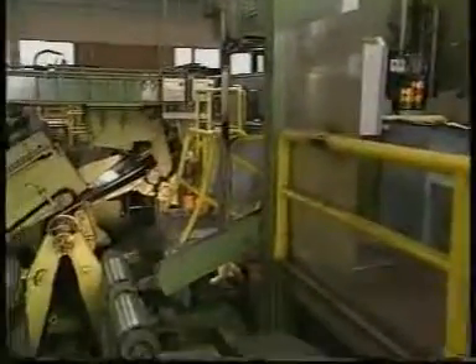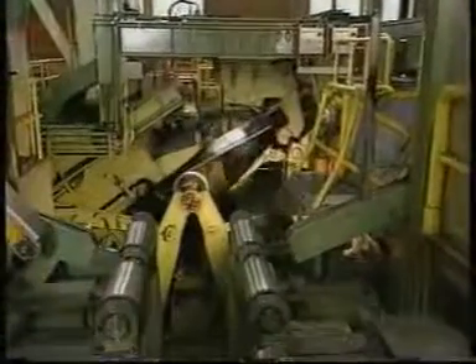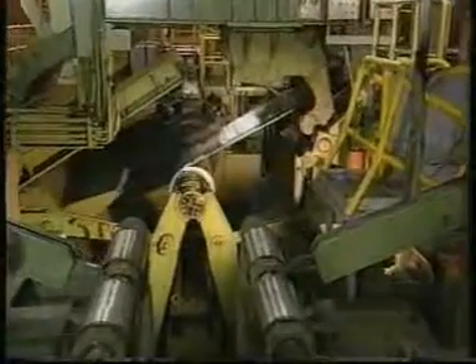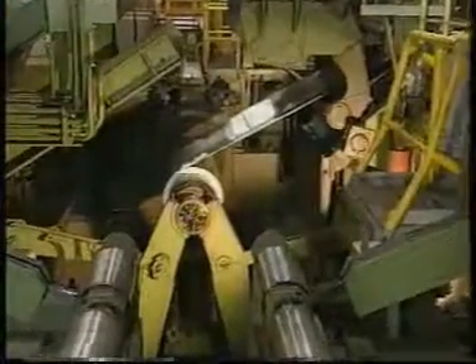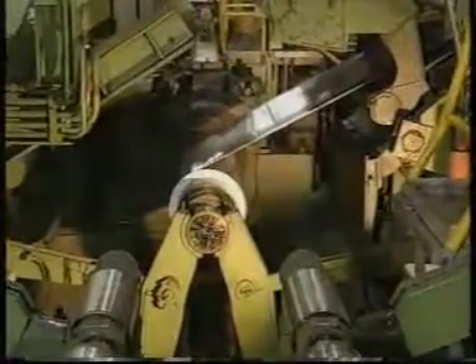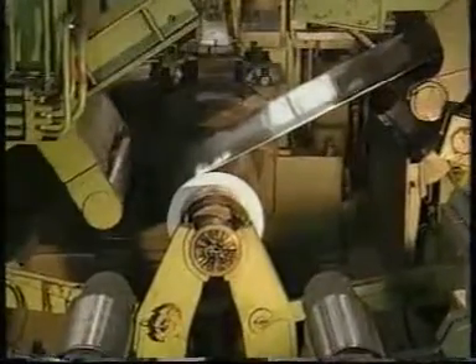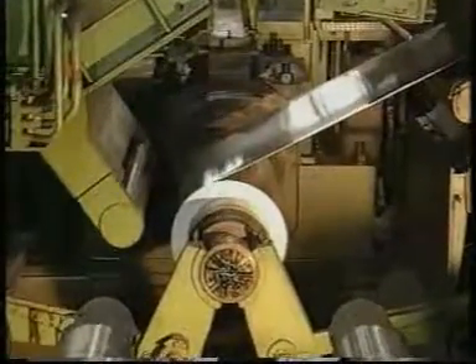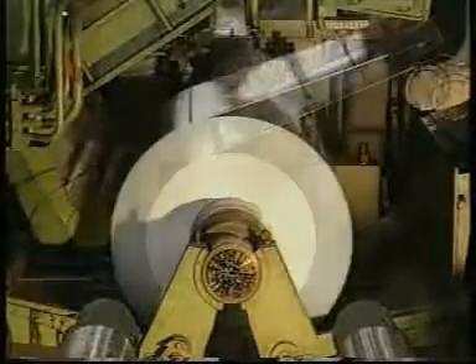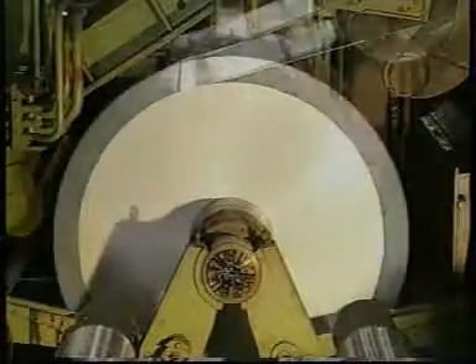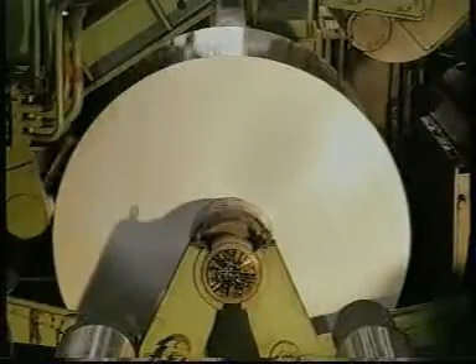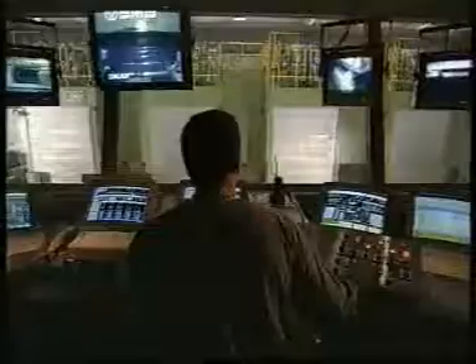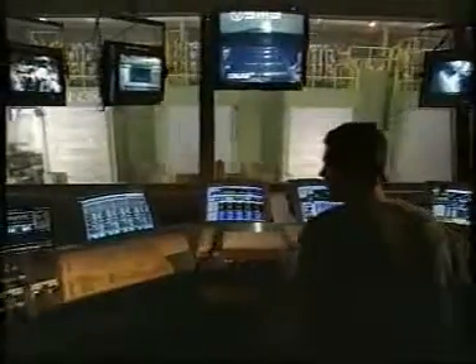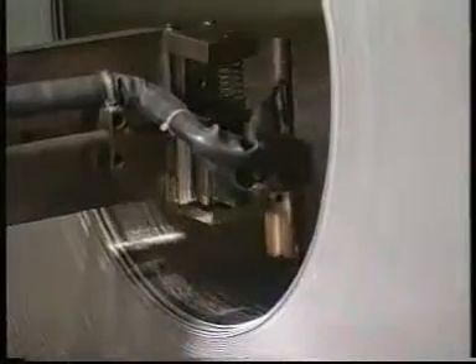In only one pass, the gauge can be further reduced down to only 2mm, and that at a rolling speed of 480 meters per minute. The strip is finally trimmed and rewound on the mandrel, producing coils of up to 2.7 meters in diameter. Integrated measurement and control systems, coupled with CVC technology, guarantee consistently high quality through all these processing steps. The inner laps of the finished coils are subsequently spot welded for transport.